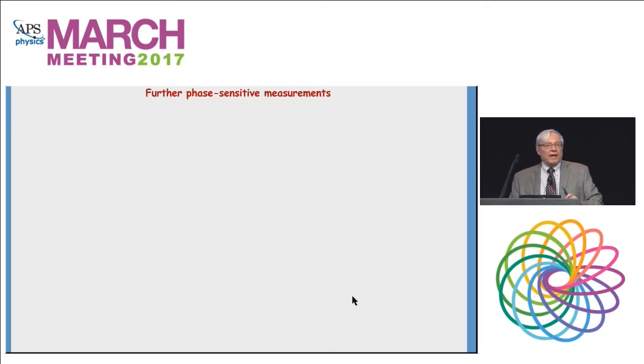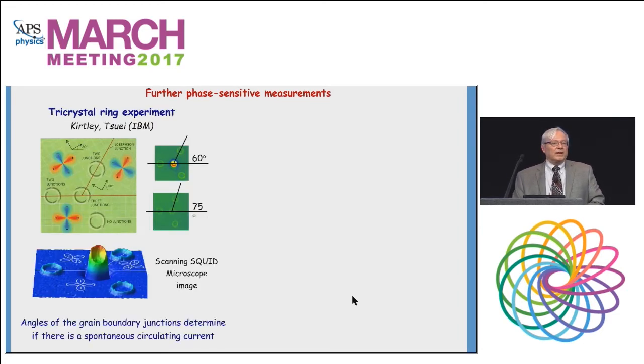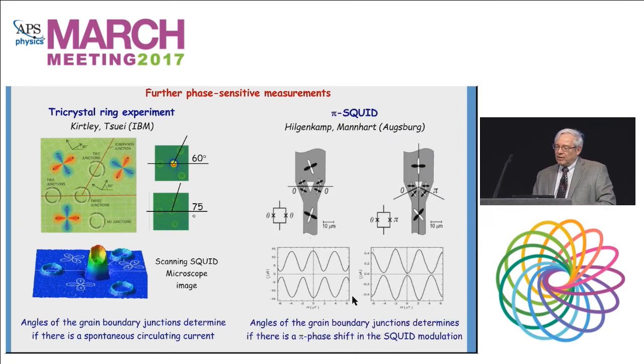There were very shortly after that some very elegant experiments. The tricrystal ring experiment done by the IBM group. You can make little rings like Cam was looking at, and you can use a scanning SQUID microscope, and you can either see a signal or not a signal depending on whether you have an odd number of junctions and you get a pi phase shift. A very nice experiment done by the Augsburg group was to make a SQUID in this fashion, and you can see here directly the shift in the interference patterns as you put a pi shift in or not. So you can either have two zero junctions or a phase shift of pi inside the junction.